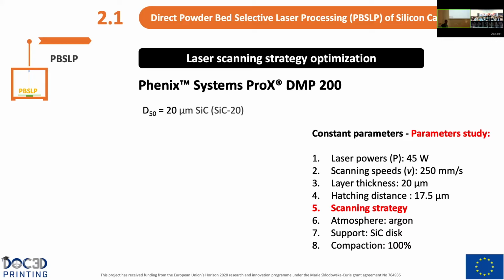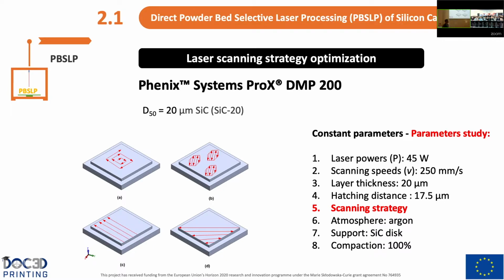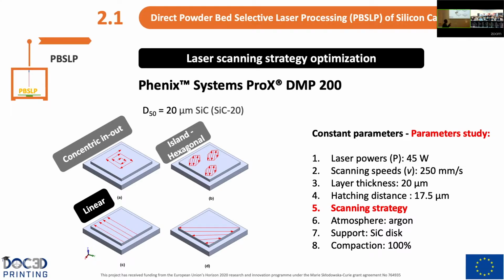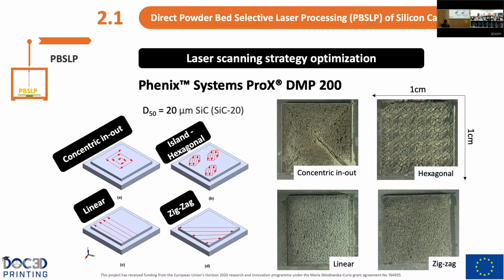Then, regarding the optimization of the scanning strategy, here we decided to keep the other parameters constant to just see the effect of the strategy during the process. Here we use 4 different strategies. The first one, concentric in-out, following this path. Then, island scanning with hexagonal shapes, following this path. Linear scanning, following this path. Each time the laser arrives at the end, it's turned off and comes back to the beginning and repeats the process. And finally, the zigzag, which follows this path. So regarding the experimental results, we can observe how different the process is just by modifying this strategy.